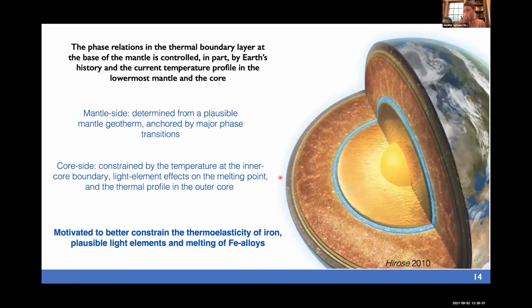Okay, so moving on to the final part, essentially we've talked about the core mantle boundary and the potential for iron-rich MgFeO to explain some ultra-low velocity zones, in particular those with a 2-to-1 ratio or even a 3-to-1 ratio, where the shear waves are reduced by up to 3 compared to the P waves. So this can be explained by the elastic properties of magnesiowüstite with anywhere from 10 to 30 volume percent in that assemblage. But going beyond this, there is uncertainty in the rheological properties of this phase assemblage and how strain is partitioning.